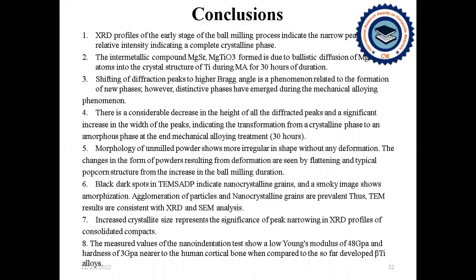Conclusions. From the XRD study, we conclude that at the early stage of the ball milling process, narrow peaks indicate the elemental powders, and the intermetallic compound, MgTiO, is formed at the end of 30 hours of ball milling duration. It is because of the ballistic diffusion of magnesium atoms into the crystal structure of titanium, and the shifting of the diffraction peaks to higher Bragg angles. It suggests a phenomenon related to the formation of new phases.